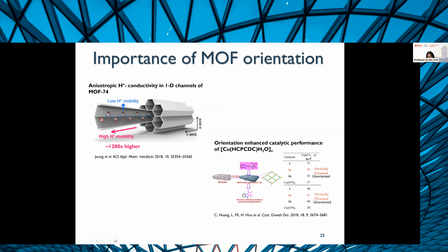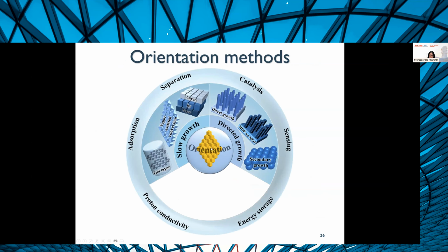Besides mass transport within the channels, one can also consider how orientation enhances things like catalysis. This is just one example of many, where the authors grew MOF on a nickel film. They showed that when they had vertically oriented crystallites versus non-oriented crystallites, the catalytic performance was significantly enhanced in the vertical case versus the unoriented case. So we thought, okay, it's really important to orient MOFs. And actually, there has been quite some work. It's not been an unrecognized problem.